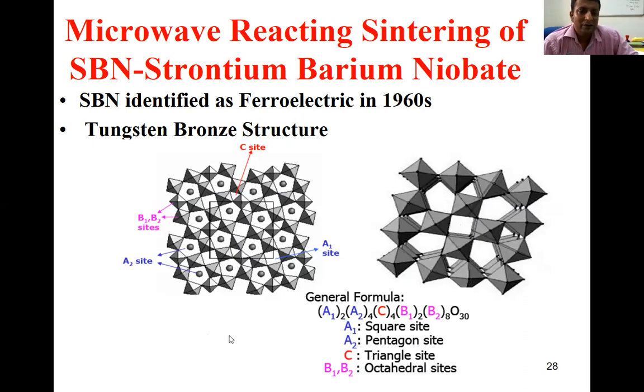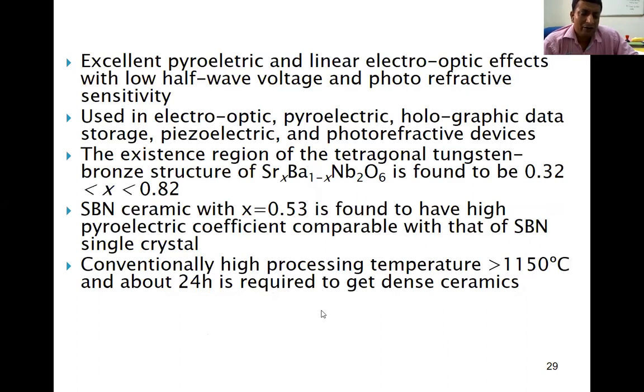This is another system that we took, the strontium barium niobate system, which is a tungsten bronze structure ferroelectric system. We processed it via this microwave processing technique. It has applications as a high dielectric constant material, and this SBN we chose has better pyroelectric properties. For pyroelectric applications, this material we chose, and we processed it via microwave processing.